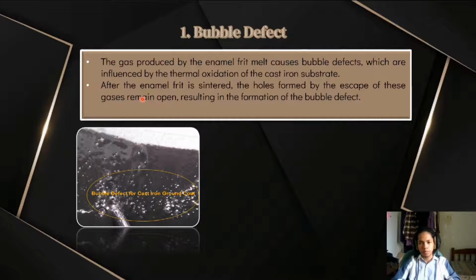So the first one is bubble defect. Bubble defects happen when the gas produced by the enamel frit melt, which is influenced by thermal oxidation. So when we cast the cast iron, the oxidation between the cast iron pan and fire will produce bubble defects. After the enamel frit is sintered, the hole formed by the escape of these gases remains open, resulting in the formation of a bubble defect. As you can see here, this is a bubble defect on the cast iron ground.